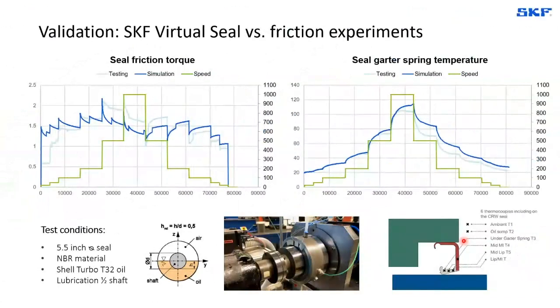So then the question is also, with this capability, how good are we when compared to reality? We did some internal tests, and here I'm showing an example. It's just a single case over many that were run internally. What we can see here is, for a certain speed cycle here in green, going all the way to 1000 RPM, over a certain duration of time, the friction torque response in simulation versus what was measured in testing.